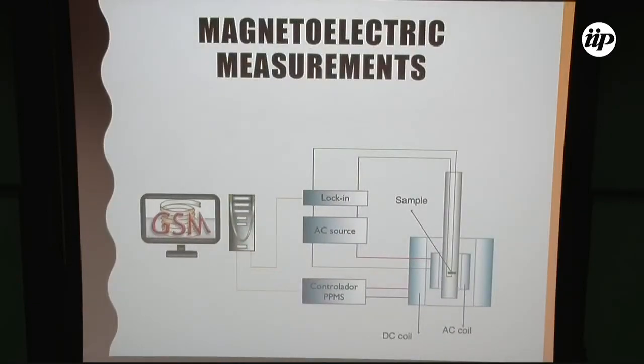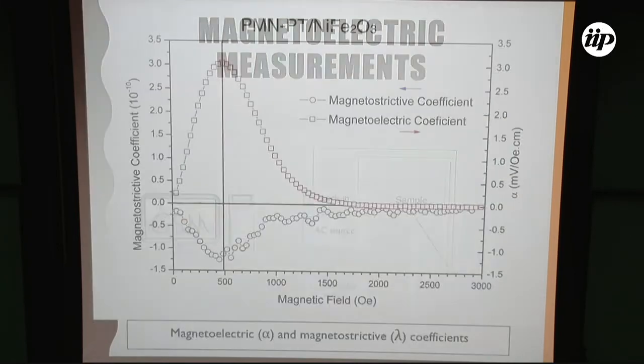The magnetoelectric effect can be measured by applying an AC field to the sample, using a lock-in, and applying a DC field at the same time. The AC field is induced by the movement of the magnetic domains, and the DC field changes the magnetization of the sample.